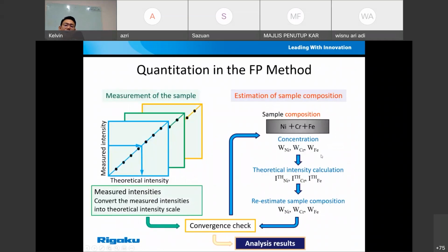How it does this is that we have a measured intensity and also a calculated intensity. The software compares these two. If the estimated calculated intensity matches the measured intensity, it means the two systems are matching, and then we can give you the analysis result. If it is not matching, it adjusts the theoretical intensity calculation formula, re-estimates the composition, and checks it again. If matching, then this is the result.